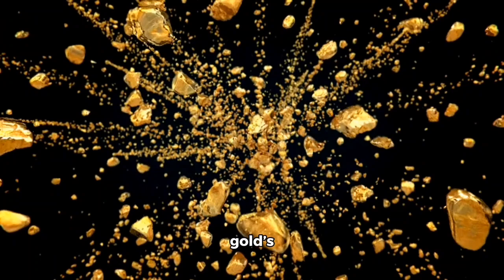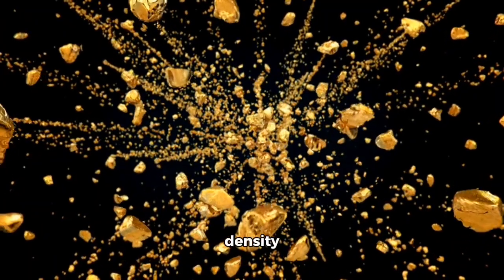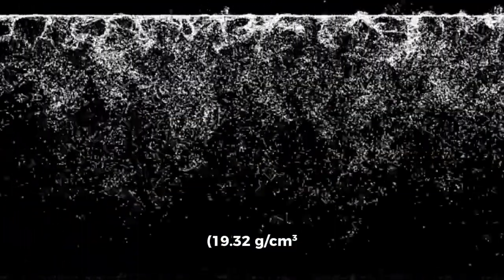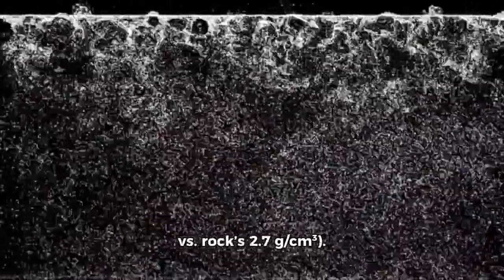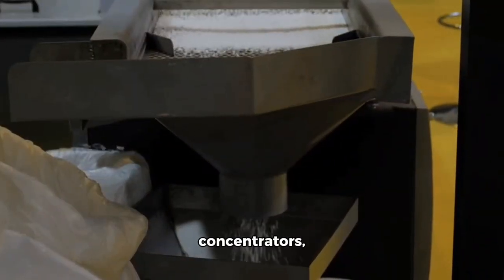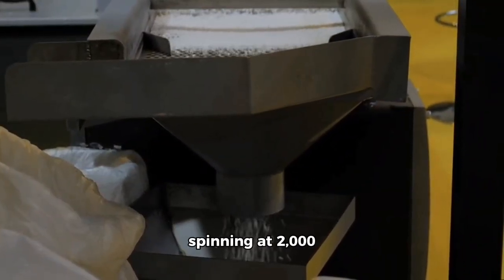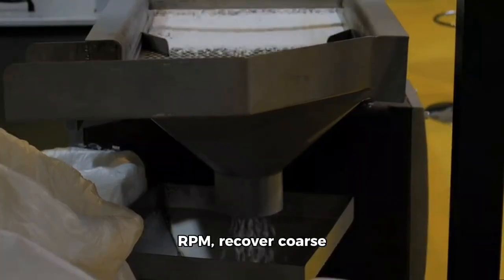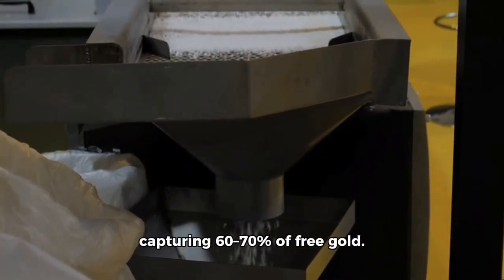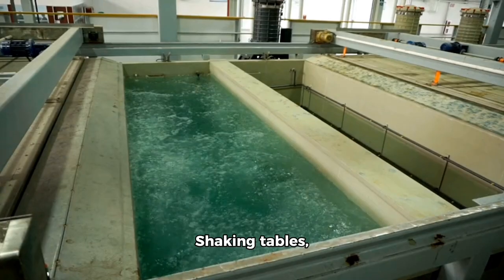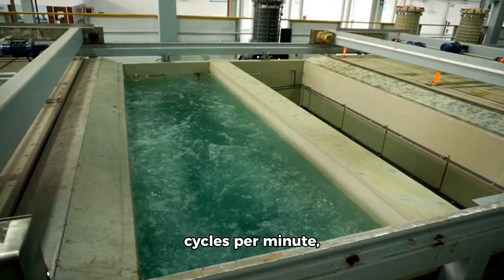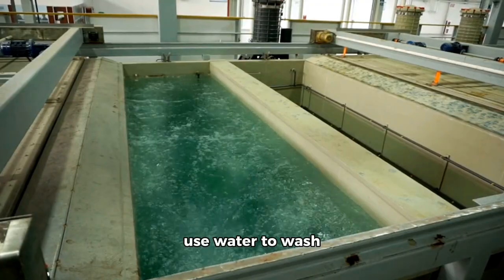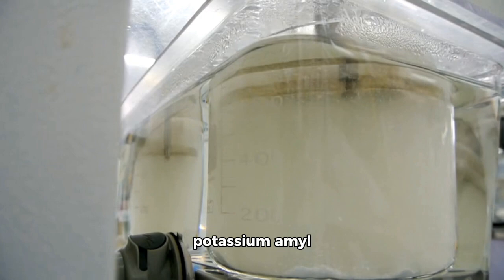Separation and concentration isolate gold from worthless gangue. Gravity separation exploits gold's density, 19.32 grams per cubic centimeter versus rock's 2.7 grams per cubic centimeter. Knelson concentrators, spinning at 2000 rpm, recover coarse gold particles, capturing 60 to 70% of free gold. Shaking tables, vibrating at 300 cycles per minute, use water to wash away lighter materials, leaving gold behind.